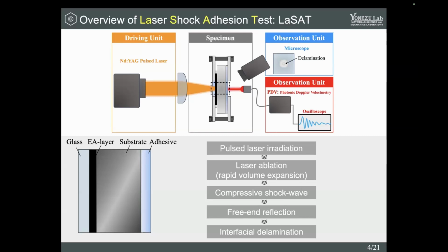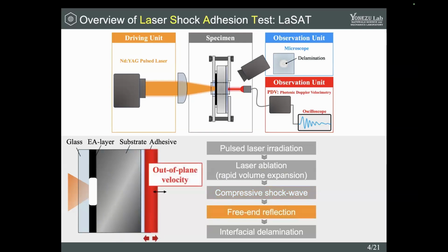In the first step of LASAT, the pulsed energy laser is irradiated to the EA layer. Then, by the EA layer absorbing the light energy, it rapidly expands in volume and vanishes. This is laser ablation. Due to laser ablation, plasma pressure is applied and a compressive shock wave is generated. When this shock wave propagates through the specimen and reaches the opposite free surface by free end reflection, the compressive shock wave turns into a tensile shock wave.